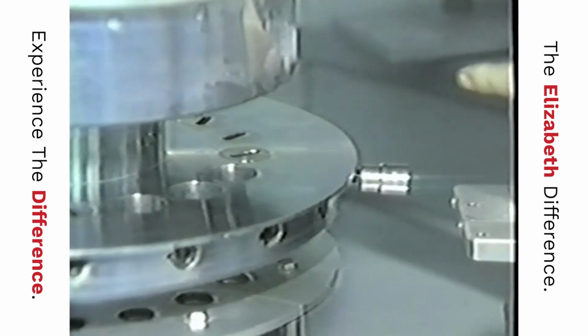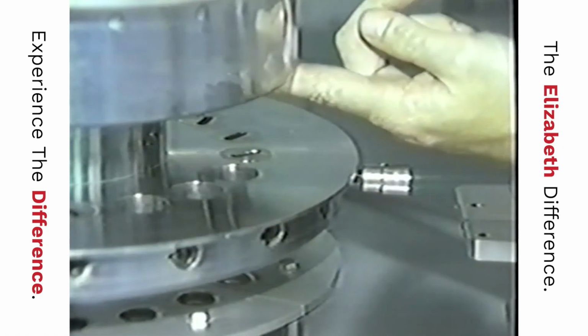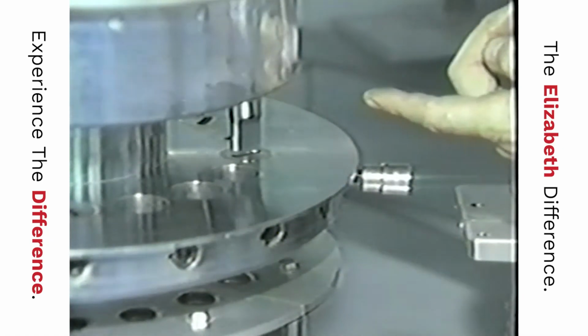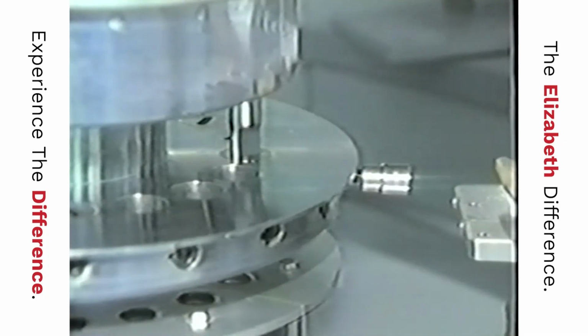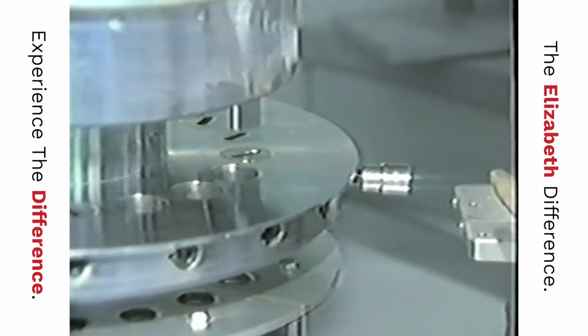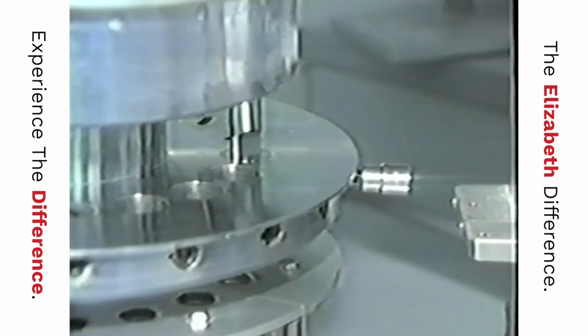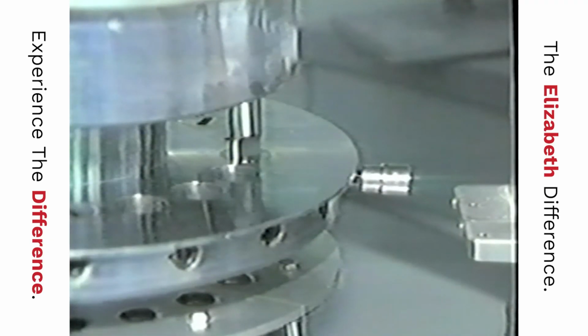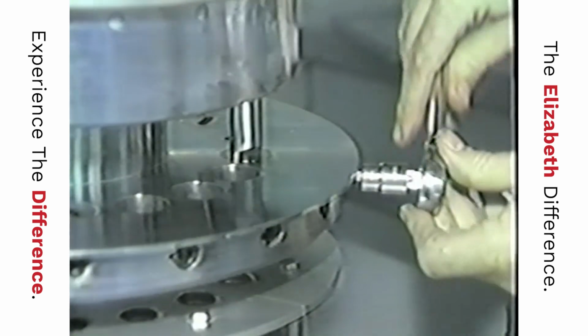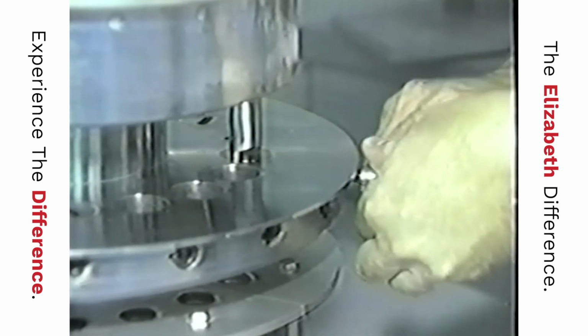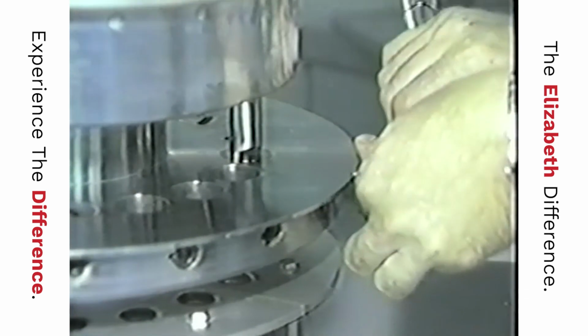The punch can now be reinserted and checked for alignment. Not all dies will fall right into place. Therefore, care should be taken when reinserting the upper punches. If the upper punch is allowed to fall, a nick in the cup edge is likely to happen. A special die ID wrench should be used when setting the dies. The wrench allows the operator to turn the die without its removal. When punch-to-die alignment is correct, there should be little or no drag between the punch and die. Friction between these two surfaces can cause scoring in the die bore and premature wear on the punch tip.